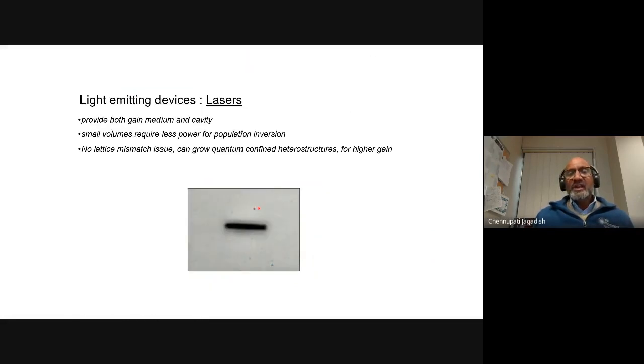So it turns out if you take a nanowire and shine light from the top, the light comes out of both ends of the nanowire, because the nanowire acts like a waveguide. And both ends of the nanowire also act like mirrors, as I was mentioning to you. The nanowire has a refractive index of 3.4, and the air has a refractive index of 1. That refractive index difference creates mirrors.